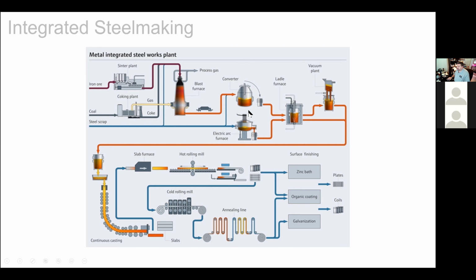So after we go through the converter, or if we melt material in an electric arc furnace, the material then tends to go to what we call a ladle furnace. The ladle furnace is essentially, we tap the steel into a refractory lined bucket. It's a really big bucket, but that's probably the easiest way to describe it: a refractory lined bucket. And we take that and we sit it underneath essentially just what would be an electric arc furnace roof. It's smaller and with a much less powerful transformer.